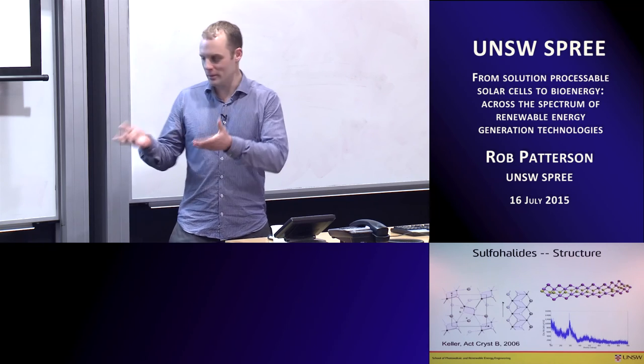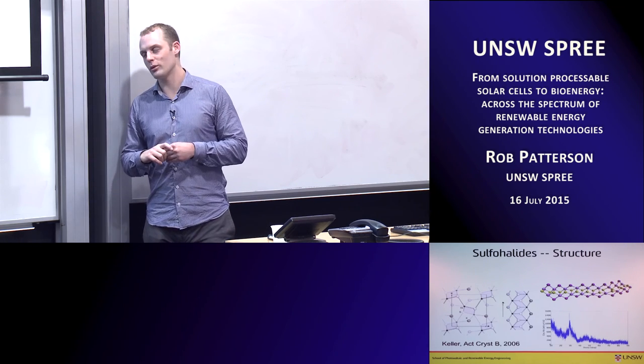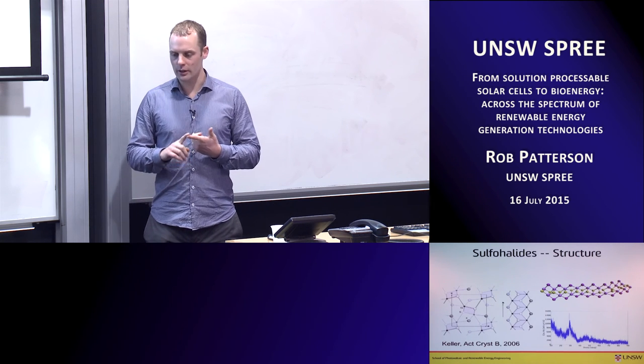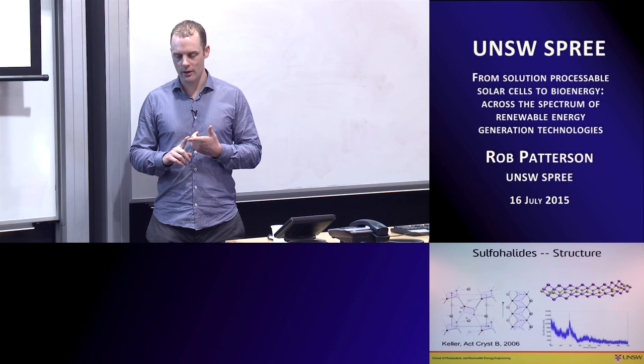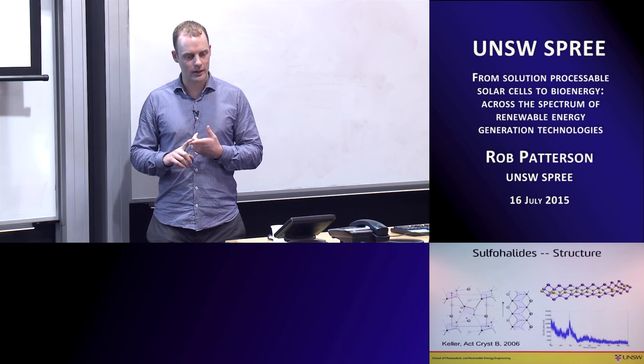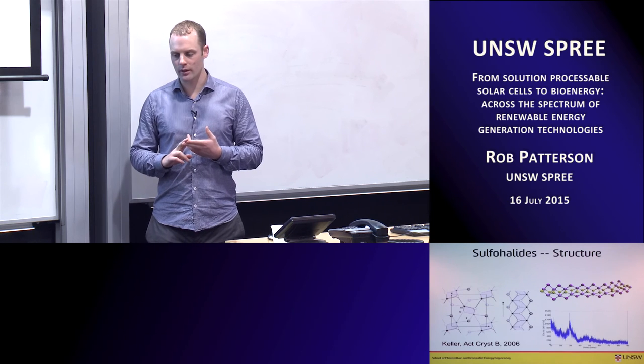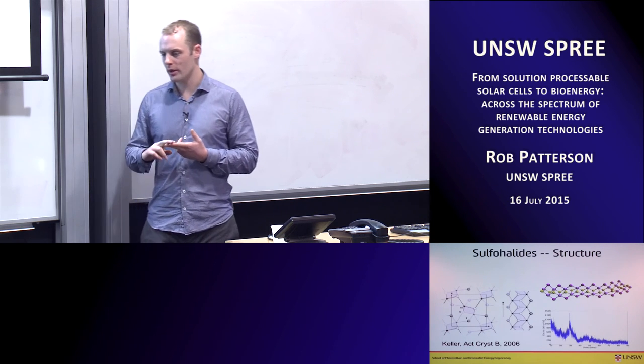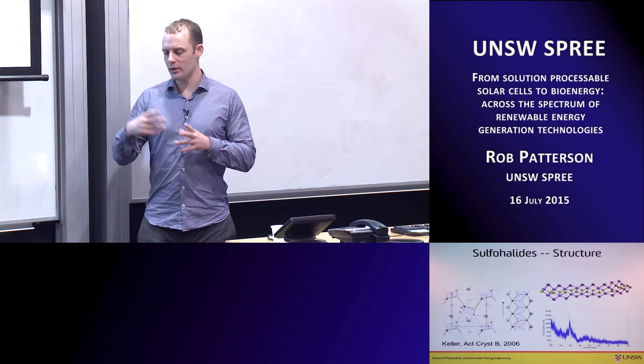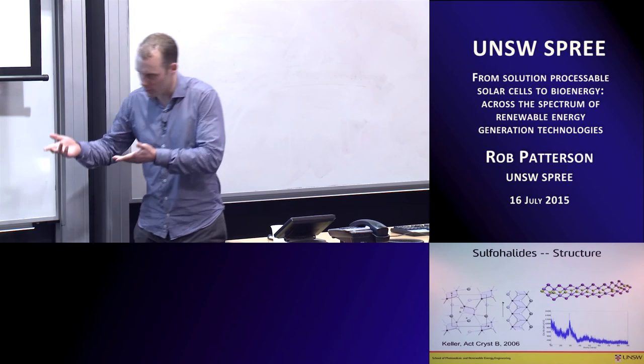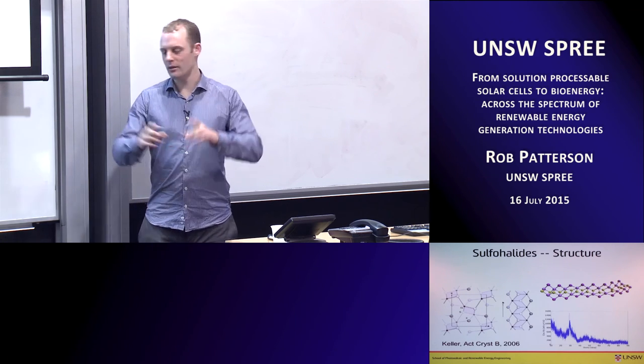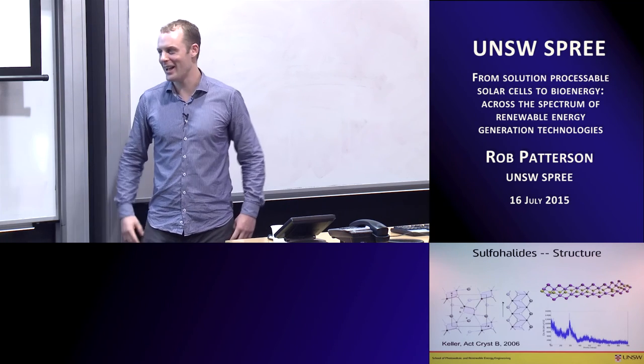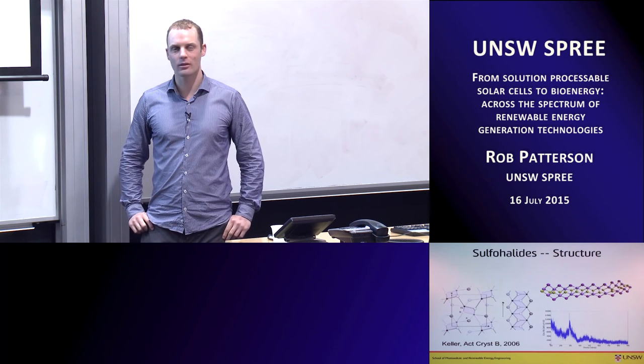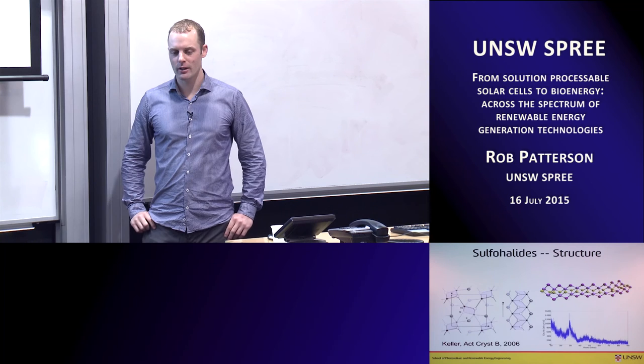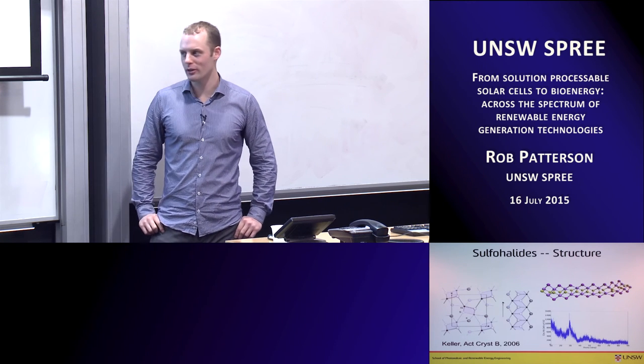There may be many reasons for that, some of which may have to do just with the way the cell was made. But one of the pieces of literature about this material says that their experiments, and I forget exactly the technique, at Argonne National Labs in the States, were able to show that the binding for the hole on the ligand is actually quite shallow. So meaning that, yes, if you were able to connect this thing to other molecules, and those molecules were conductive, you could potentially take the charge out. That's in the very last line of their paper, so I don't know whether they pursued it or not. That paper's from 2006 or something, so I think if they thought it was promising, they might have followed up.